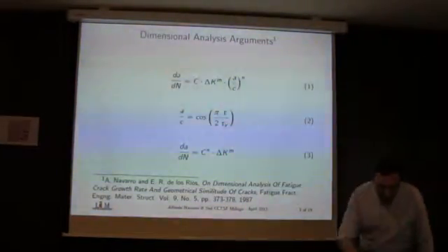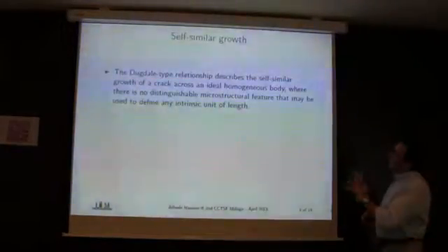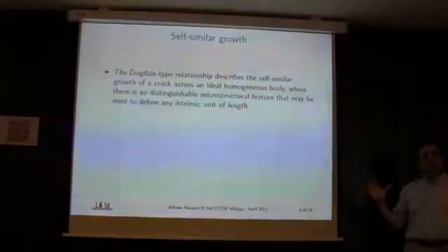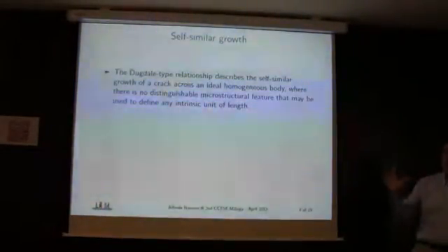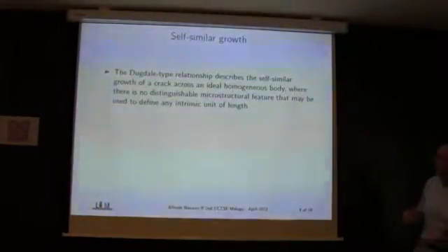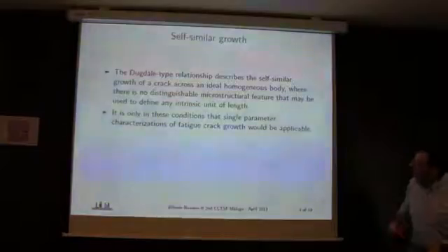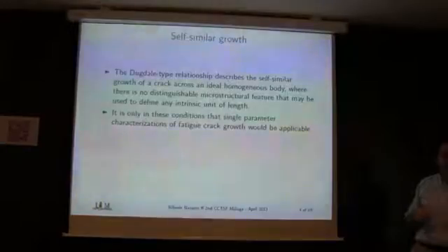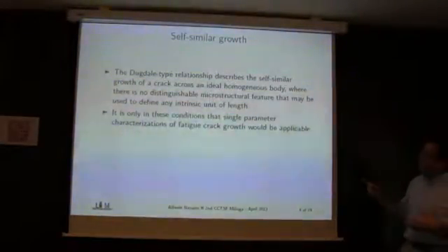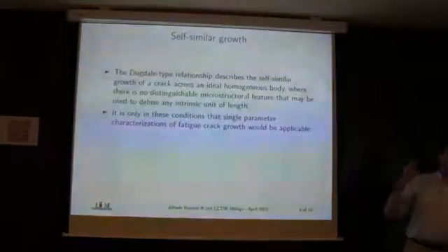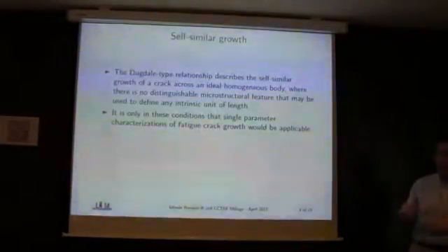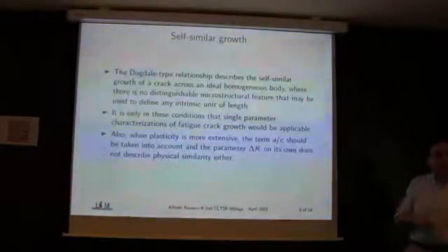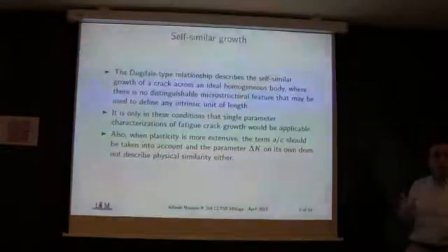The important thing here is that the Dugdale relationship really describes the self-similar growth of the crack, right? When you have this crack growing in this infinite medium, you always have the same problem. It's just a question of changing the scale, right? And it's only when you have this self-similar growth that the single-parameter characterization is valid. If in the problem that we're considering the applied loads are a bit higher, we have a substantial plastic zone, and in this case, obviously, the term a over c should be taken into account, and then the Paris law ceases to be valid, and you have to have another parameter.